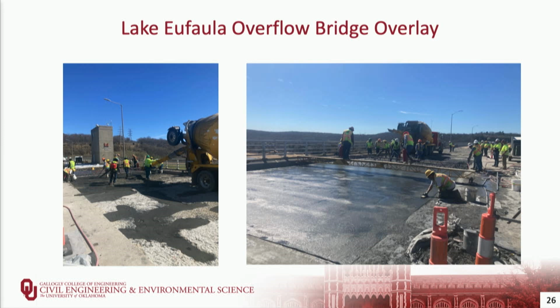Here on the left, you can see placement of the overlay. They used a material that was actually mixable in a ready-mix truck, so they were able to do 5 cubic yard batches in a ready-mix truck. They'd bring that out onto the bridge. They would place the low spots first, and then come back with the complete overlay that you see there on the right.